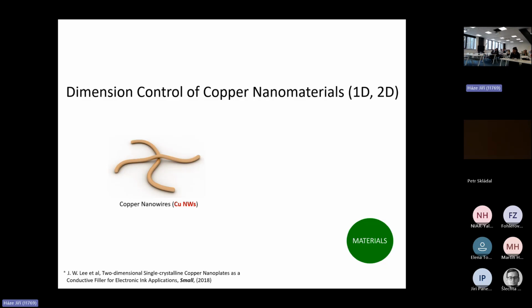Nanowire, right? It's point contact. It's very useful for the transparent electrode, and silver nanowire as well. And nanosheet is a completely different feature, as I'm going to show you later, but this is a single crystal. And this base plane is the 1, 1, 1 plane. When you stack them on each other, where the nanowire is point contact, it may make plane contact. So when you think about electroconduction, larger contact is better, right?